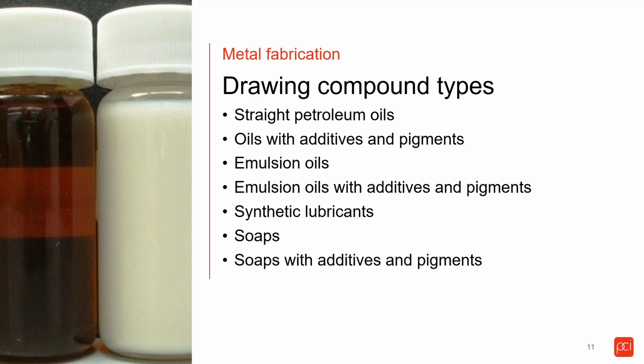The most common drawing compound you're going to see is straight petroleum oils. They're typically very easy to clean off. Very rarely do we see difficulties in the field dealing with just straight petroleum oils. We do run into a little bit of a problem whenever you have a straight petroleum oil that has additives or pigments in it that are designed to help even more with a deeper press. So sometimes those additives and pigments can be very difficult to clean off. So that's where you run into a little bit of trouble.